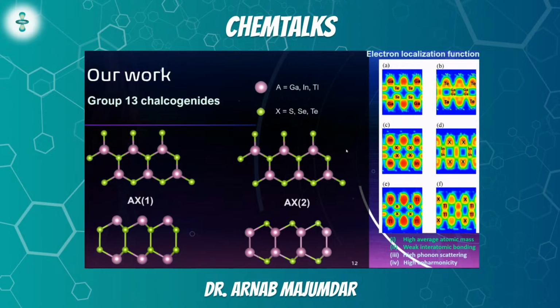Now the second one was weak interatomic bonding. Why? Because the weaker the interatomic bonding is, the lower will be the elastic constants, and the thermal conductivity depends on the elastic constants very, very strongly. So if we can get lower elastic constants, that means our thermal conductivity also has a very high chance of being low. So let's look at the diagram on the right.